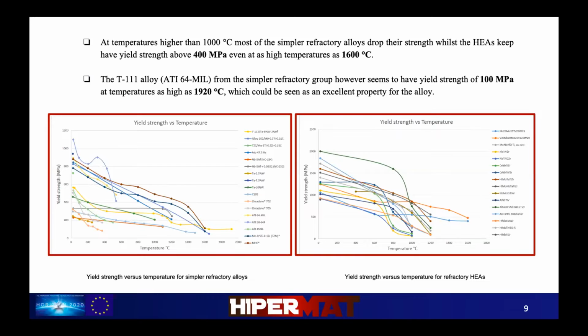Here there is a comparison for simpler refractory alloys on the left side graph, whereas yield strength versus temperature for refractory high entropy alloys is on the right side. It is interesting to note that above 1000 degrees Celsius, the simple refractory alloys drop their strength, whereas the high entropy alloys maintain their strength above 1000 degrees Celsius, above 400 MPa, even at 1600 degrees Celsius.